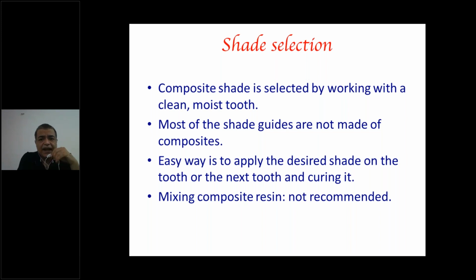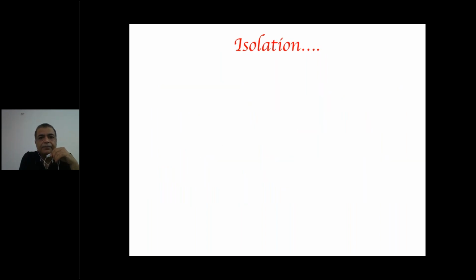And to achieve a desired shade, I do not recommend mixing different shades of composites. When you try and mix, what happens? Air voids are there in the mix, and when you cure it, you will have air bubbles in your restoration, which might crumble with time, and the restoration may fail.